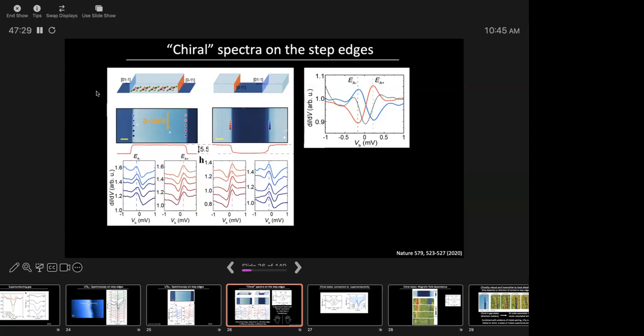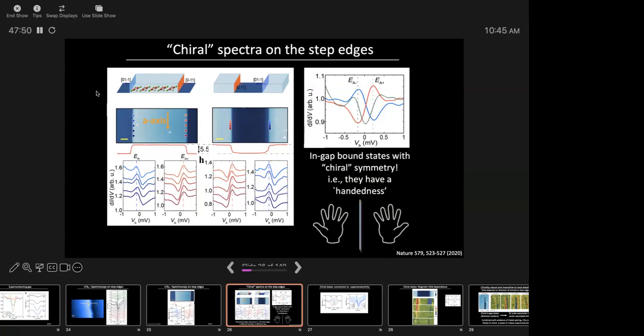So a couple of things here. Here's the superconducting gap in dotted line. These two peaks on either side are exactly symmetric. If you look at these two peaks together, you have particle hole symmetry. The dips are also exactly symmetric. So all that is great. And these things have a handedness, meaning that this peak is sensitive to which direction you are facing on the surface. So there's a chirality here.